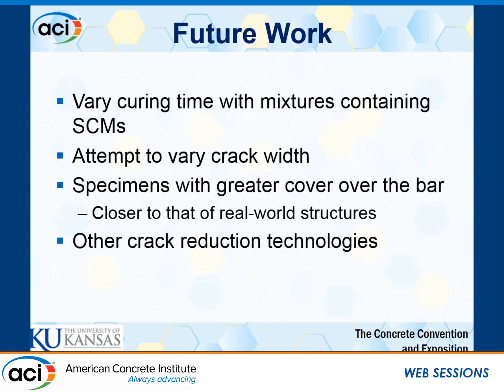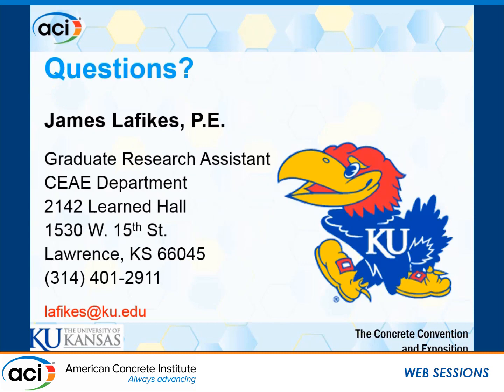So other series will attempt to vary crack widths some more. It would be really great if we can get some specimens that only have 1 mil wide cracks again, because that's pretty significant if we can move forward and conclude that even 1 mil wide cracks can initiate early corrosion. Also, to get a more realistic situation in terms of bar cover, most bridges have 2 or even 3 inches of top cover over those reinforcing bars. So we'll see if we get different results when we vary the bar cover. And finally, looking at other crack reduction technologies and admixtures. So with that, I'm happy to answer any questions. Thank you.